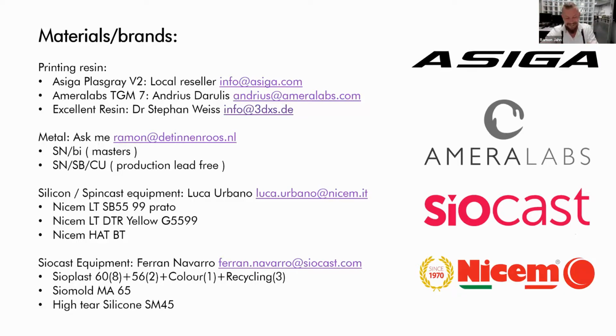But when I form this into a mold, it could happen that when I take them out of the mold, they can snap. Because they will be heated in a vulcanizer at 90 degrees, and with the force of the silicone, when you take them out, probably they will snap away. So you can only use them one time, which is not too bad if you make a prototype mold, because you will make metal masters anyway. But if you want to make a production mold and you want to make new molds with the same models again, then I would advise the Ameralabs because it's very flexible, so you can reuse it.